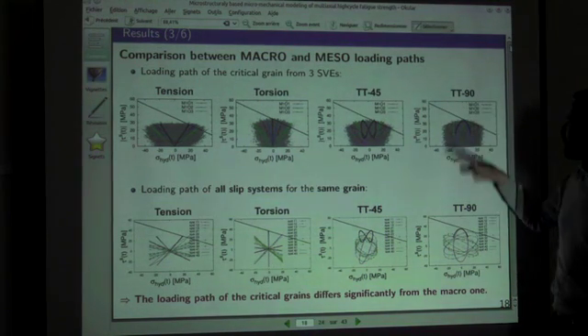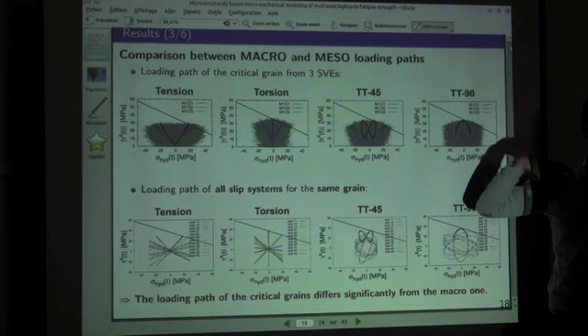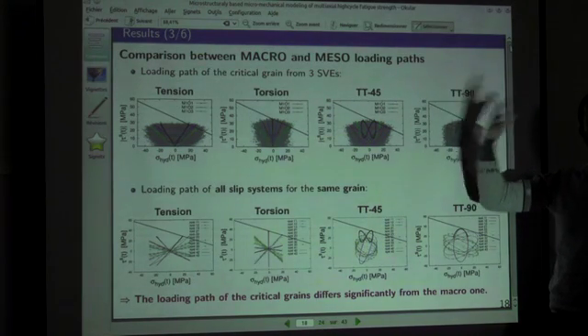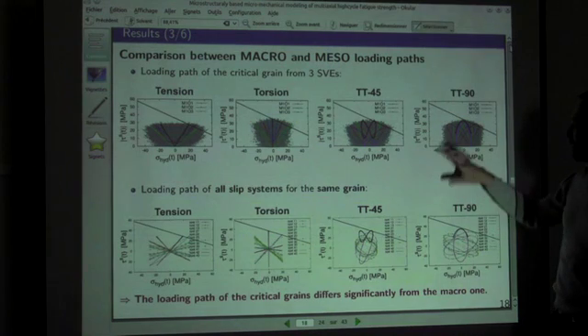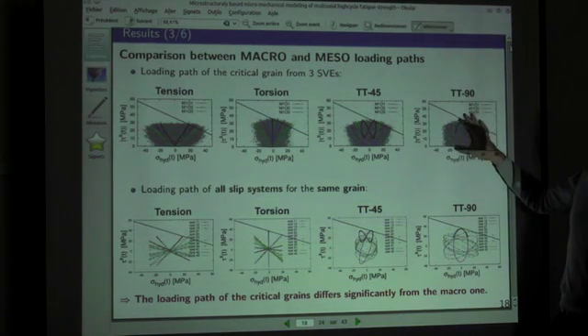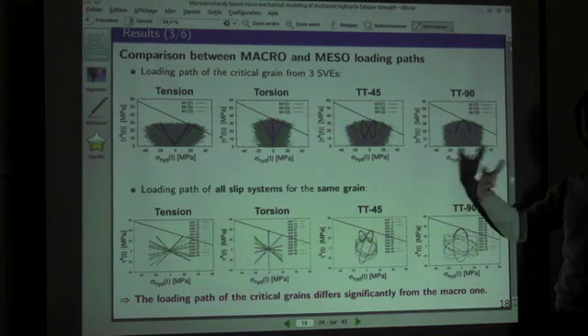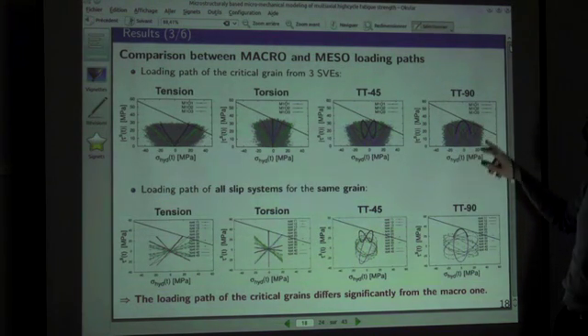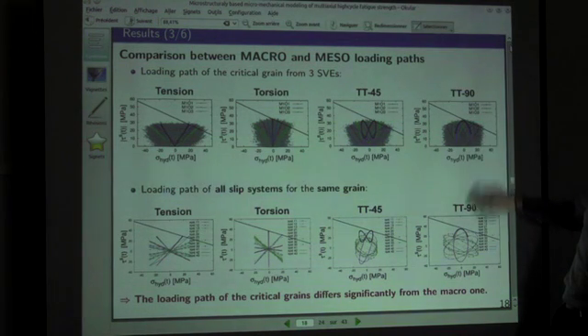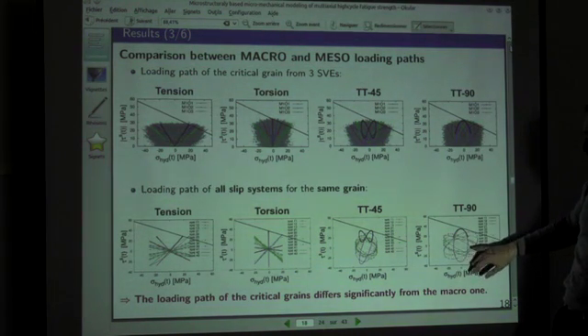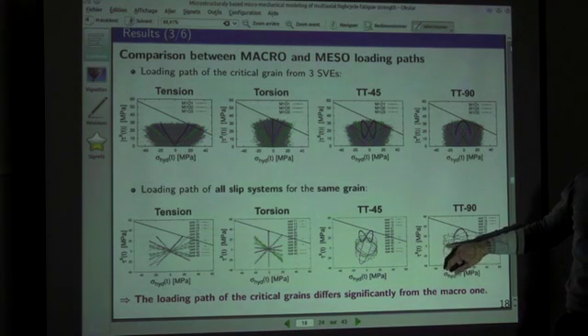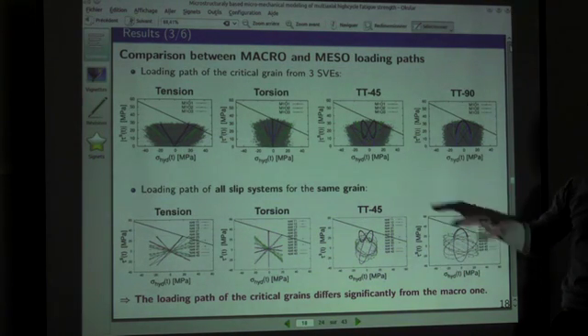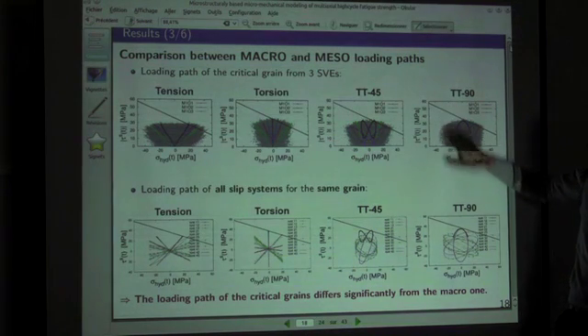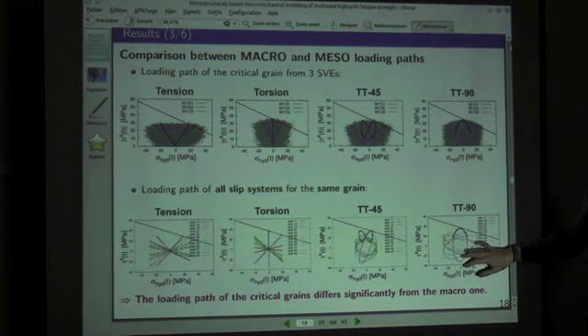So maybe the thing that we can think about is that when we try to interpret some effect of non-proportionality, and if you look at this picture, maybe the macro analysis is not a good one. Maybe you have to go to a smaller scale to understand some effects. And for example here, you can also analyze the effect of the loading on the different slip systems. So here it's in between different microstructures. Here it's for the same critical grain, but on the different slip systems of the grain.